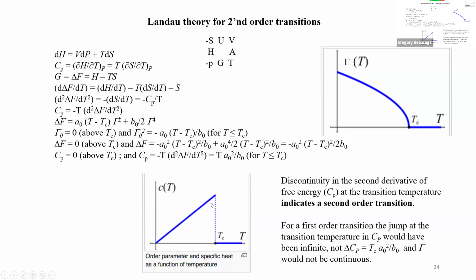So the enthalpy of transition would be the integral. When you measure heat capacity in the DSC, you have two pans, and you're heating them to keep the same temperature between the two pans. So you have to put more heat into the pan that has stuff in it because it has heat capacity. Heat capacity is a measure of dq/dT, so it's a measure of the enthalpy that you're putting into melting. When you get to the melting point, you have to put a lot of heat in just to keep it at the same temperature because it takes heat to melt the crystal. That's the first order transition, and Cp will have a peak in it. In a second order transition it's continuous through that and changes slope, so you just have a change in the value. You don't have a peak, so there's no enthalpy of transition.